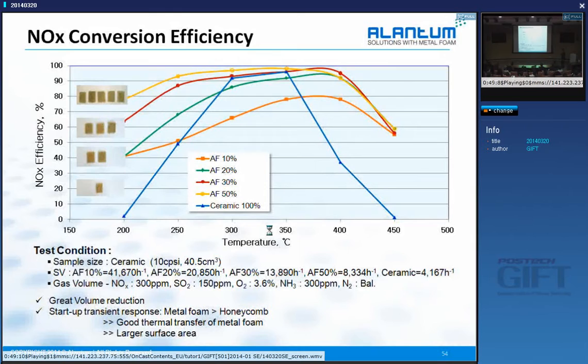If we are only using 20%, it's fairly comparable with the ceramic, right? So this tells you that we can make a great volume reduction. And then also another thing is, next slide shows that, our starting up temperature is much faster. Starting time is much faster. So that means once you stop the operation, then just restart it, we can reach that efficient range much faster.